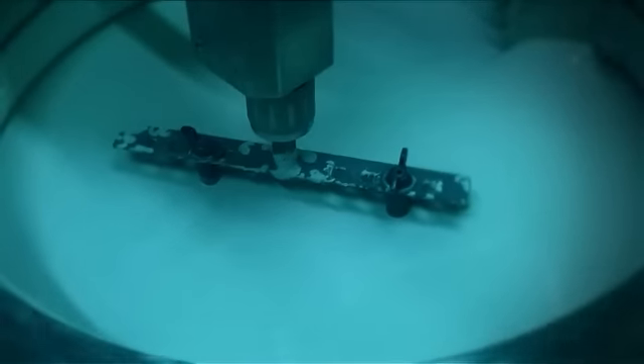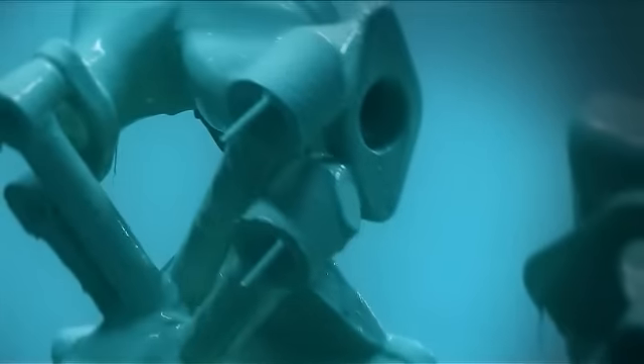The setting up of what later becomes the cast shell is a very long procedure. The wax tree is dipped 7 or more times into the slicker, sand-coated and cured to achieve a thickness of the shell wall, assuring adequate stability for the metal casting. With conventional methods, this procedure takes several days or even a week, sometimes even longer. By applying our special drying method, the duration of this procedure can be cut to 3 to 4 hours.